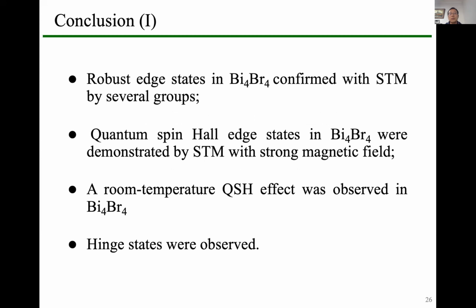Because in the first experiment we don't have variable temperature and we don't have a magnetic field, we only observe these edge states at the step edges. So we can say this is a preliminary result, an early stage result, but it is consistent with the calculations. Later on, this experiment was essentially confirmed by the second group, from Hossain. They observed quite similar behavior, and then they applied variable temperature and a magnetic field and went a further step.